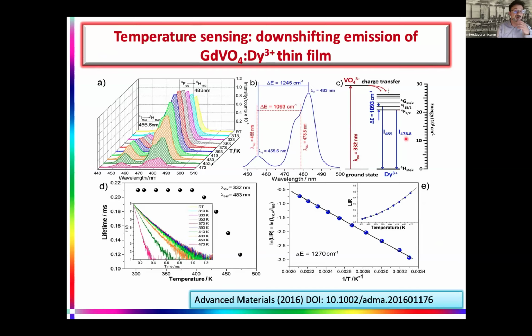So in the case of dysprosium, it can be easily excited by very strong absorption of vanadium groups in gadolinium vanadate, and then the energy is transferred to dysprosium, and these two levels serve as two emitting levels. You can see the emission spectrum on this side, at one temperature. The ratio of these two emissions is a temperature indicator, very successful.